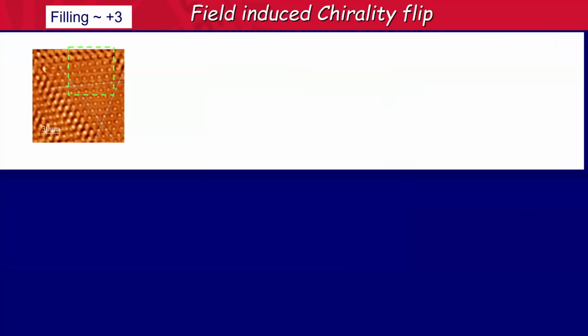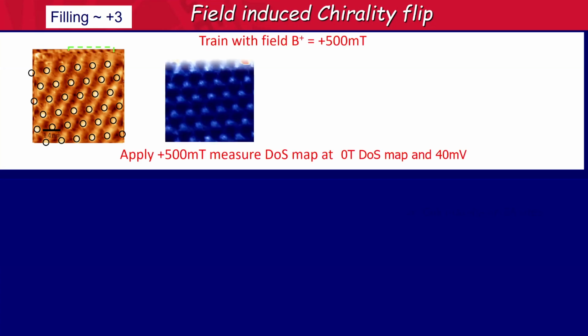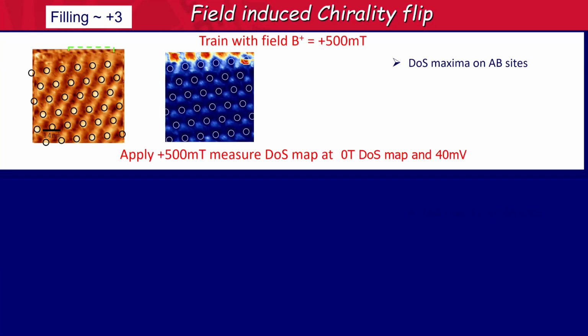Now, to get a little bit more insight into it, we again looked at the topography and we mark the AA regions where the wave function likes to sit with the black spots. And then we do what the transport people did. We trained a sample with half a Tesla positive field and come back to 0 field. And we look, where is the wave function now? You see that the yellow circles here are where the AA regions were seen in topography, but the maximum of the wave function has now shifted to the AB sites.